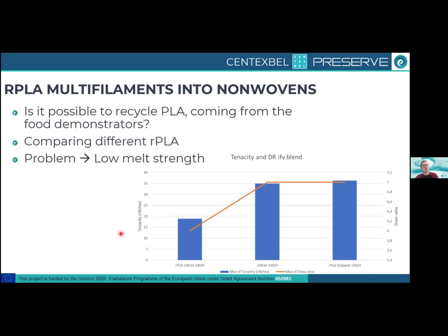The food demonstrators are mainly used in film extrusion. So taking this PLA from film extrusion into filament extrusion is already a big difficulty because of the low melt strength of this PLA. So we will need to upgrade this low melt strength of the PLA by using some additives.